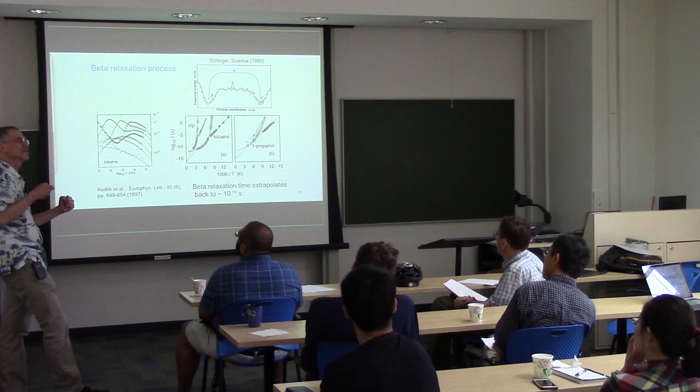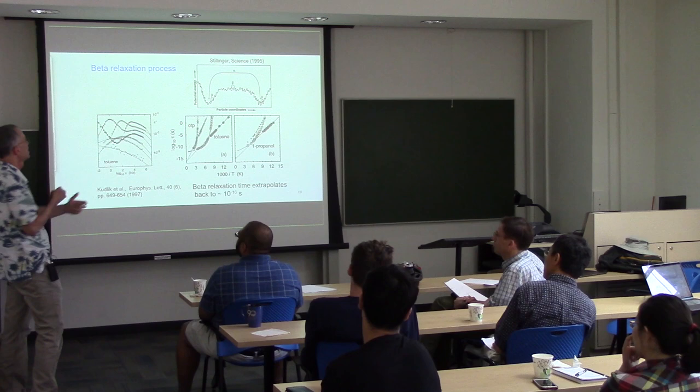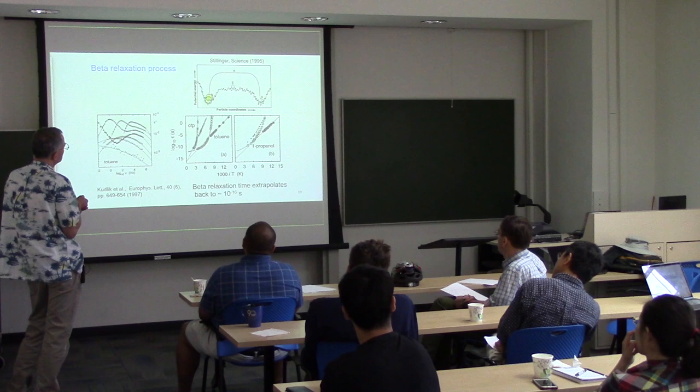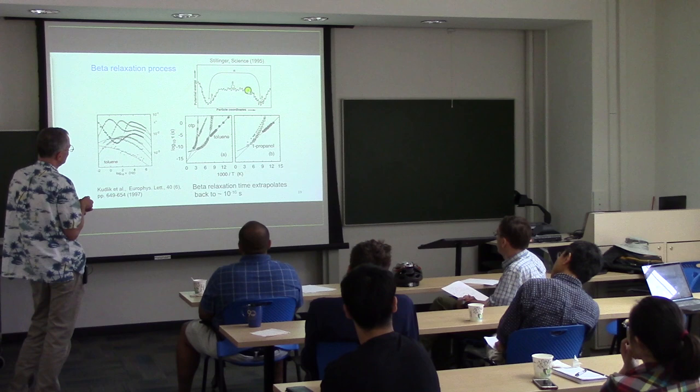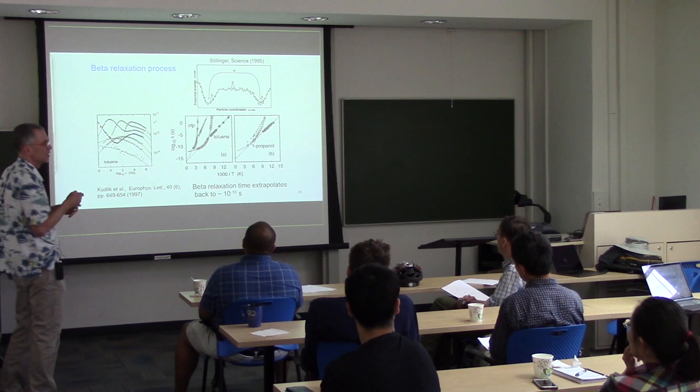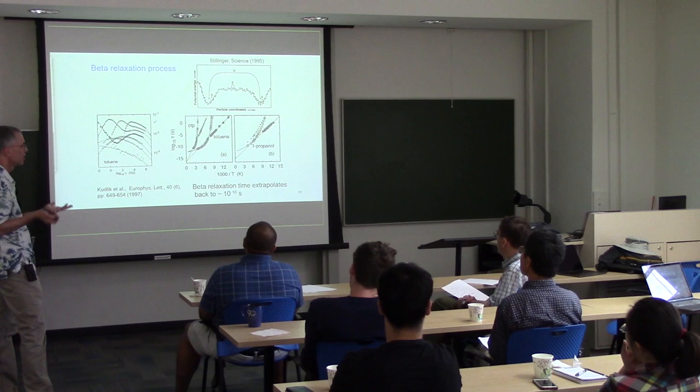And so at a really qualitative level, we can think about the process of aging or the process of molecules in a liquid finding themselves a new set of nearest neighbors. Those kinds of relaxations carry us from one of these things to the other thing. And these things are called metabasins. So when you go from one metabasin to another, that is a complete relaxation of your local environment, sometimes called the alpha relaxation process.